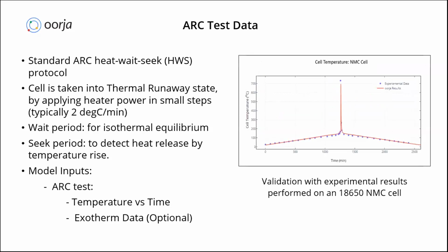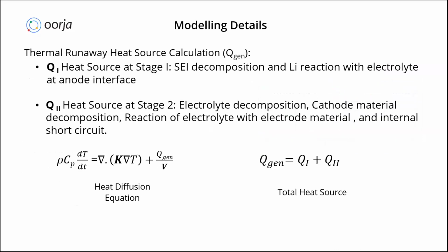So this is one of the validations we had performed for the ARC test data that we had used. Here in this case, once we get the thermal ARC data in Oorja, as I was mentioning, we estimate the different parameters responsible for the thermal runaway inside the cell itself. Based upon that, the thermal runaway heat source calculation is also done. For example, the thermal runaway happens in two stages.